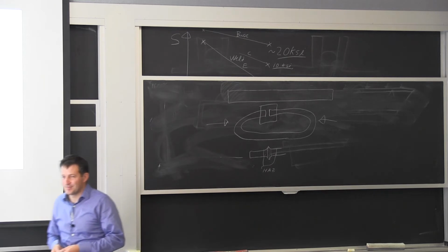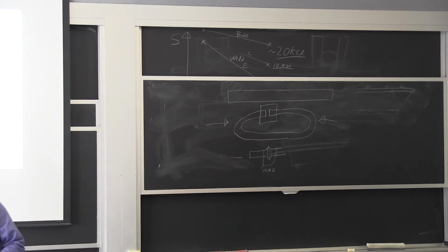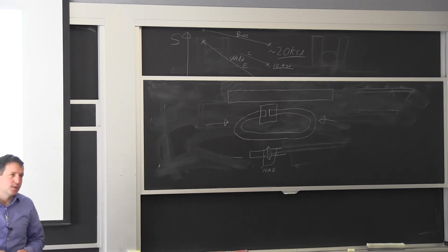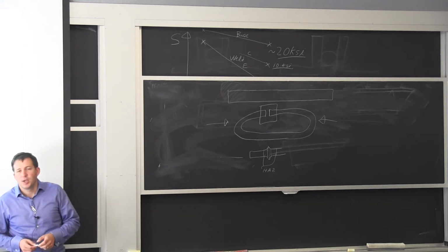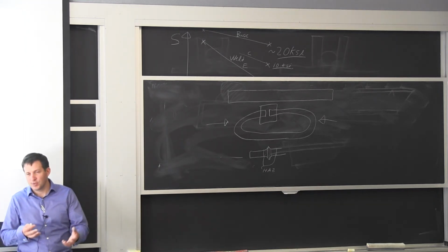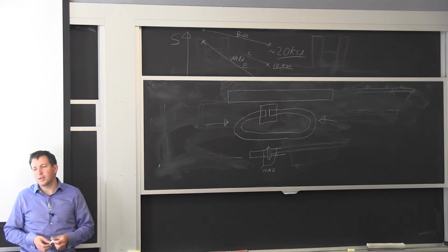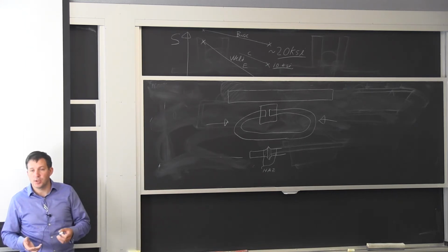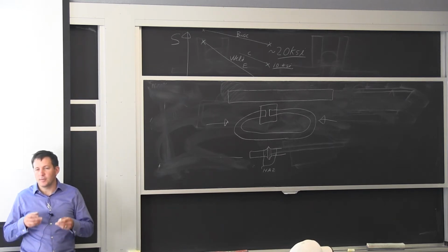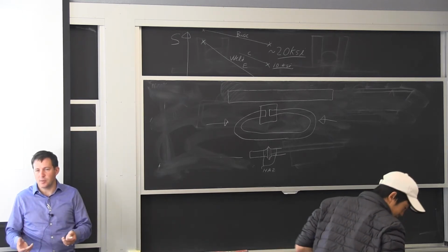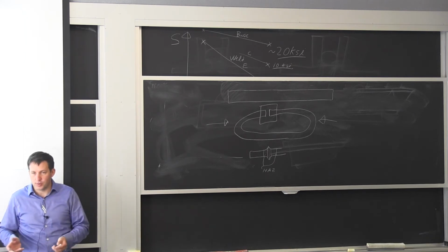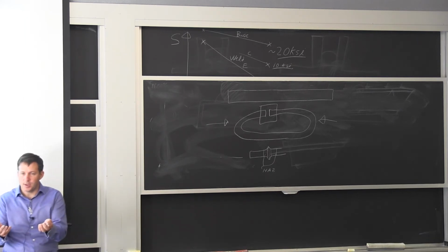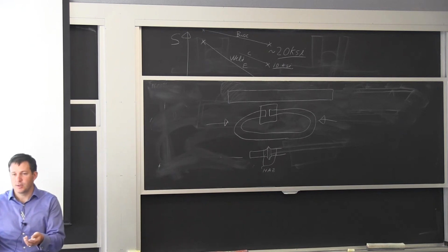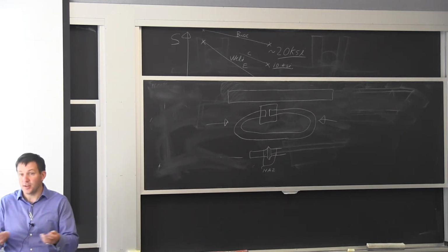What about stress relief, possibly in steel? Or strain release, for instance. So if you heat it up, would it just deform sometimes on its own? Oh, that's a good question. When you do a stress relief, you will have some distortion, and that's why a lot of times you're going to do it before a final machining operation. So if I want to make a precision assembly and I need to weld it for a certain number of reasons, I make that assembly, I heat it up so I relieve the stresses. When I come back for machining, then nothing happens.